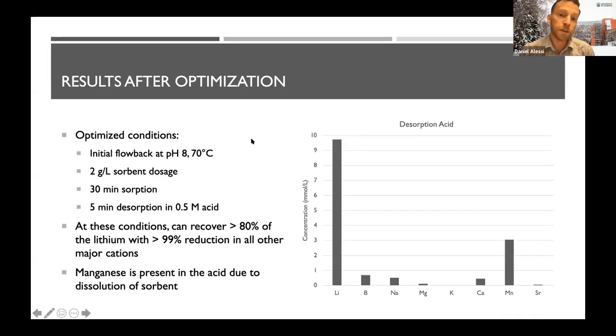So here's some real data on that particular brine. I promised to show some conditions. It ended up that pH 8 and 70 degrees Celsius were pretty good. 70 is an important number because a lot of brines return to the surface in Alberta between 60 and 80 Celsius by the time they get to the surface, so this is potentially feasible at an actual site. We used 2 grams of the sorbent per liter of fluid, so it's quite a small mass of sorbent per volume of brine. It took about 30 minutes to reach equilibrium and load up the sorbent with lithium. The desorption step, where you're kicking lithium back out of the sorbent, is pretty fast. It's actually less than 5 minutes, but 5 minutes gets you nearly everything.